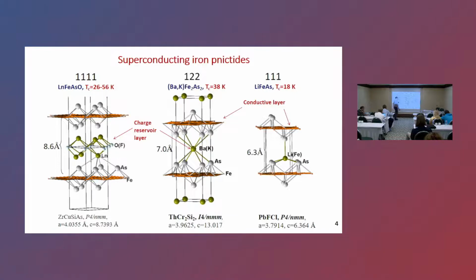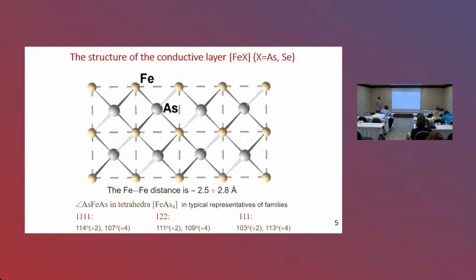We prepare a neutral layer, and this is very important for measurements by ARPES, for example, because in the case of the 122 family, the alkali earth metal stays exactly in the center between layers, and after cleaving, the layer has some charge, and this is not suitable for some measurements. The layer is a square lattice with iron atoms, and the arsenic atoms are up and under the square in this lattice. As a result, all iron atoms have a tetrahedral coordination of arsenic atoms.